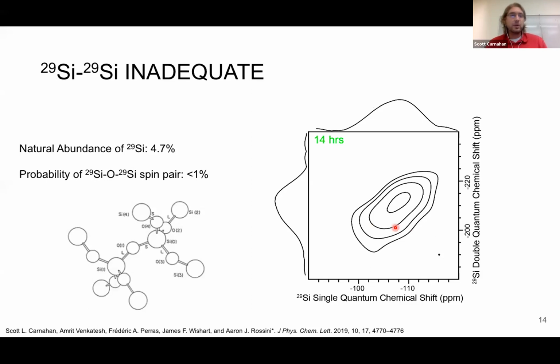What can we do with this large enhancement we're getting? Well, one of the litmus tests for how well our DNP is working is to perform a silicon-silicon INADEQUATE. This experiment requires two silicon-29s to be bound together in a Si-O-Si spin system, where they have this bridging oxygen. But what makes this experiment special is the fact that silicon-29 is only 5% abundant. So the probability of having two silicon-29s next to each other is extremely low, which really hurts the sensitivity of your experiment. And what you can see is that we're able to get this INADEQUATE spectrum in essentially just an overnight experiment. While it's not the most interesting experiment, there's only one site in quartz and you can just see autocorrelation, it does demonstrate the power of the DNP enhancement that we're able to get.